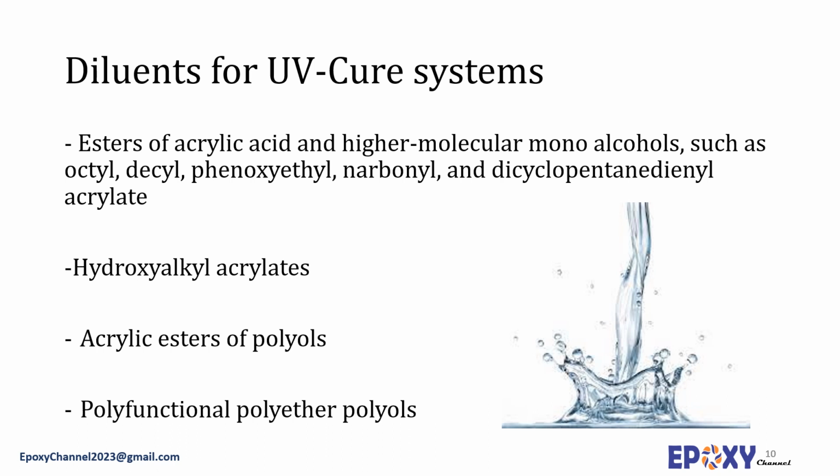For UV systems, often reactive diluents containing monoesters of acrylic acid are used. Similarly, diluents with esters of methacrylic acid are not often used due to their lower reactivity and final cross-link density. However, low molecular esters of acrylic acid often have an unpleasant odor and evaporate relatively faster, which in turn imposes higher health risks.